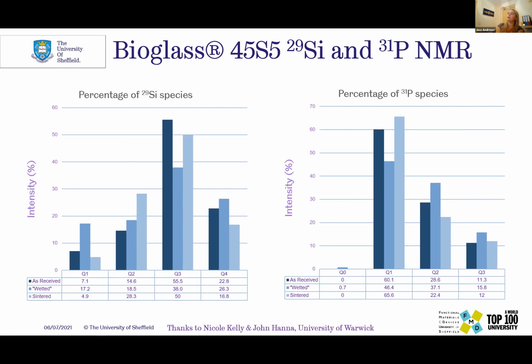We also see that phosphate ions pop out when you add the water, and then they get resorbed back into the structure. So you end up with no Q0 phosphate ions in the final material. That helped us understand the mechanism that's going on.